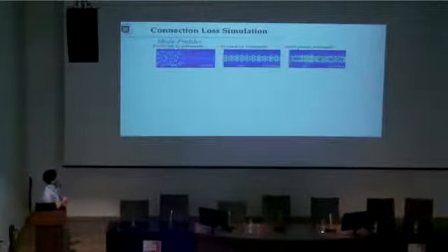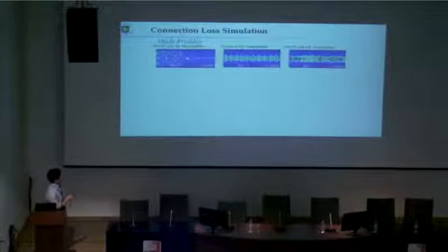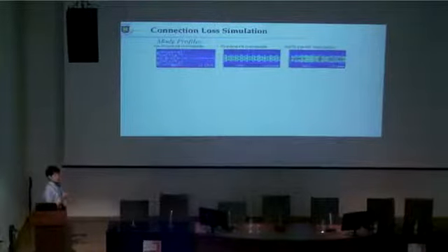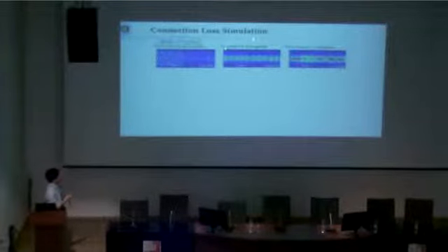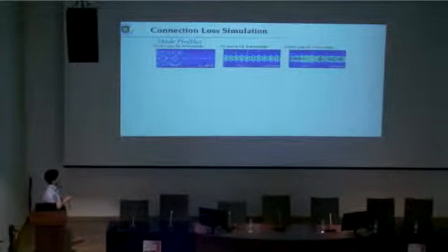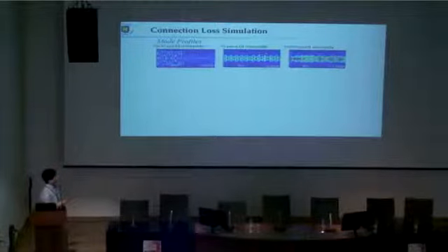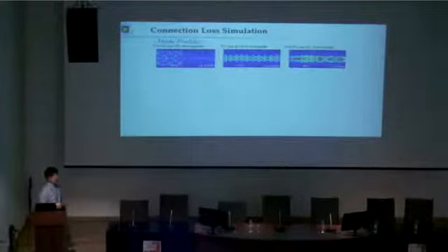In the 50 micron square core step index waveguide, all modes are extended over the whole core area, while in the graded index core multimode fiber, due to the optical concentration into the core center, the field is completely different. On the other hand, when we use a 50 micron GI circular core polymer waveguide, the modal field mismatching is not observed in this chart. And even if we use a 50 micron square GI core, we can expect a similar effect to the circular GI core as well.